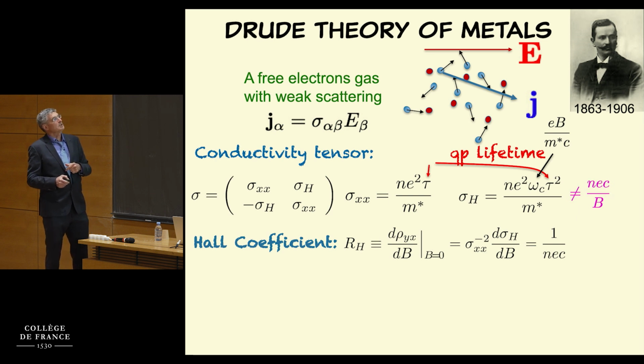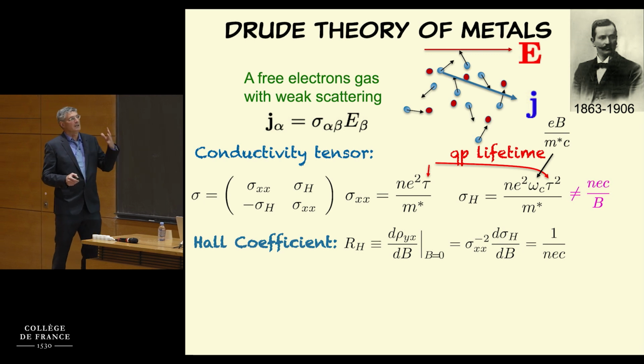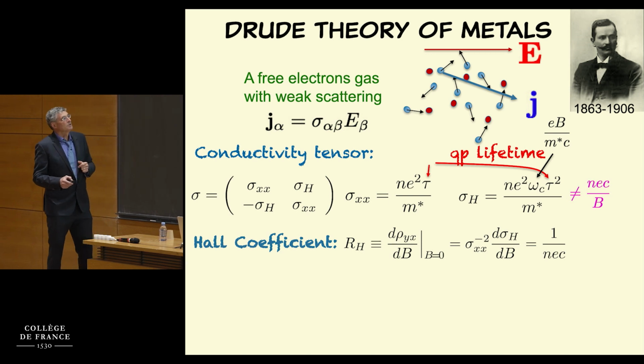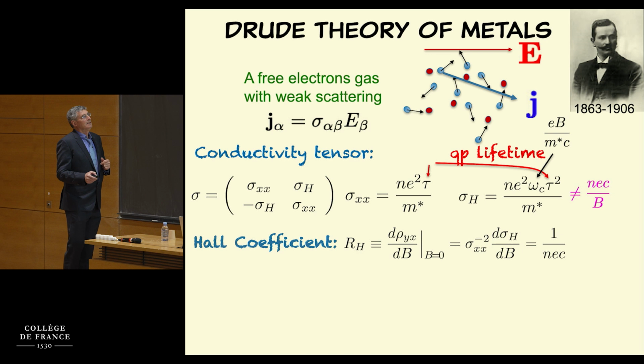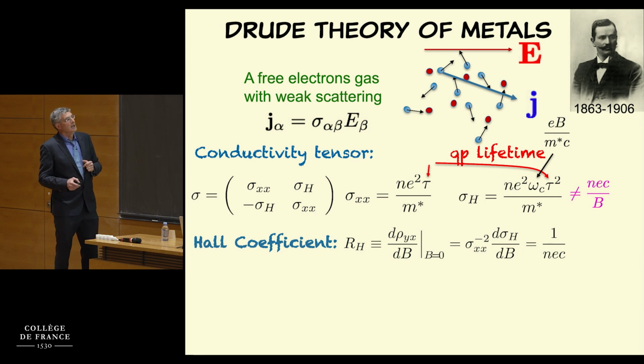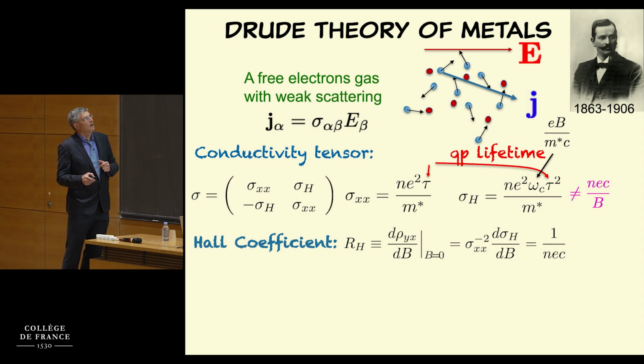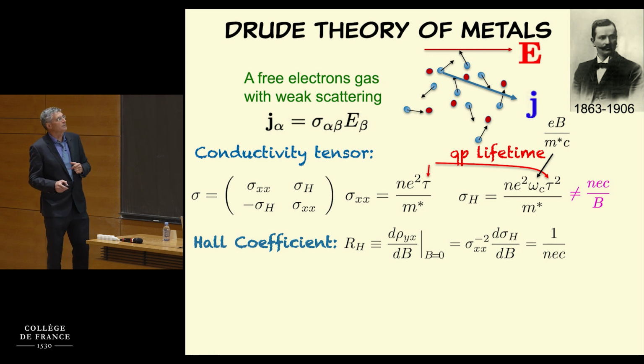The Hall conductivity, notice, depends on all these quantities and also on the magnetic field and on tau squared. So you see the Hall conductivity is very different from what we saw before in the lattice and impurity-free model. One should realize that the Hall conductivity does have all these dependencies in it. But if one looks at the Hall resistivity, which is the inverse of this matrix, calculated at weak magnetic field, you get an expression in which all these quantities like m star and tau fall off, and you're left with a very simple expression, which is 1 over the charge density times the velocity of light.